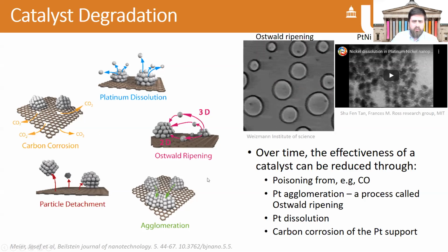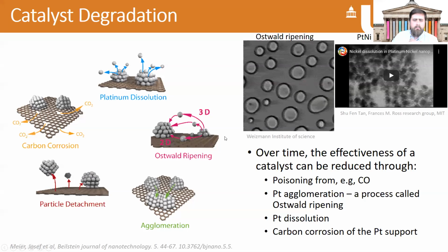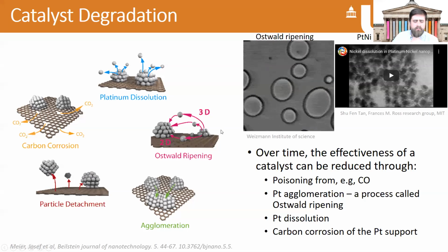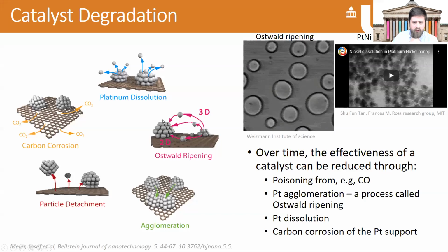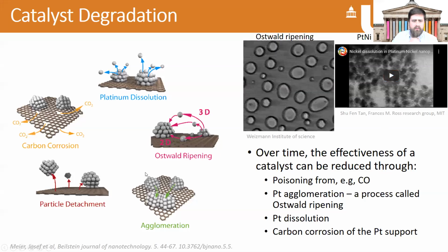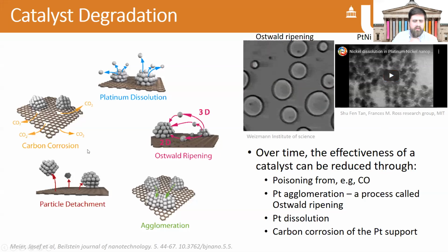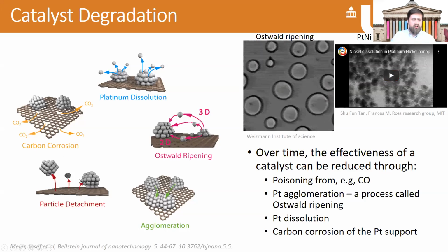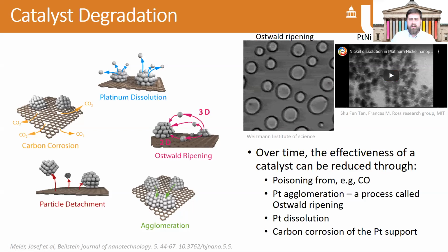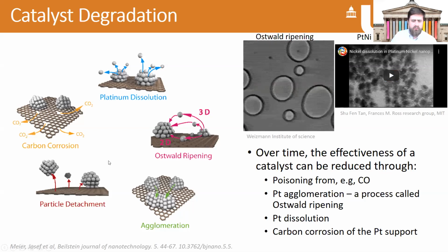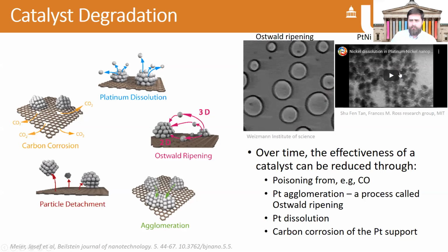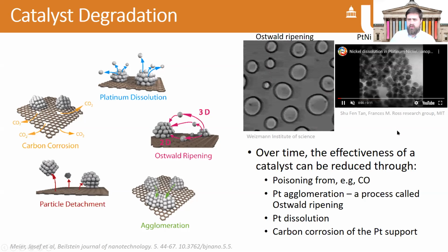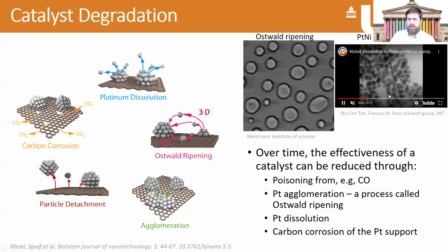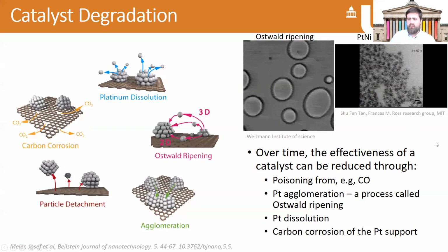There's also a process called Ostwald ripening, which is shown in this animation here, not for a fuel cell catalyst, but this is where metals end up agglomerating into larger agglomerates because of dissolving and redepositing over time. Obviously, you can have platinum particle detachment as well from the surface. When that detaches, it's no longer electrically connected, and therefore you lose one of those key components of all electrochemical reactions, that electrical contact between the electrode. There's a little video here showing some in situ TEM, some in situ microscopy of a platinum nickel alloy catalyst actually dissolving under different potentials.